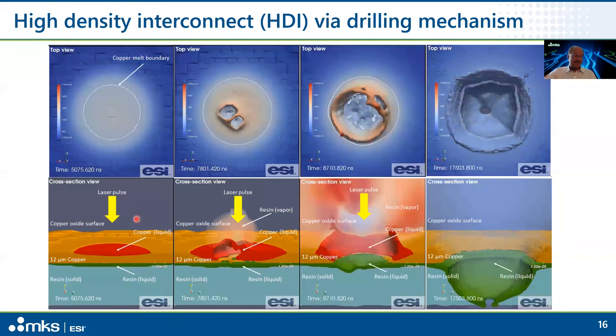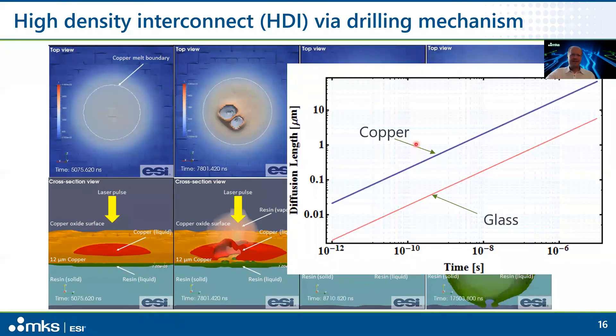We can calculate this. You have the temperature in top view and a phase diagram from a side view. The laser pulse heats up the copper oxide and converts it to copper, creating a copper melt pool. You need to get through 12 microns of copper, and recalling our diffusion length chart, if you want to go through 10 microns of copper you'll be in the microsecond regime.